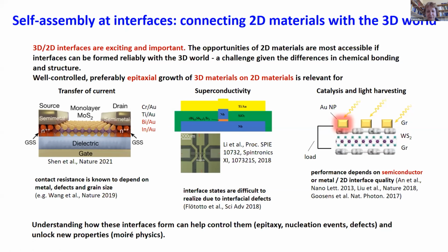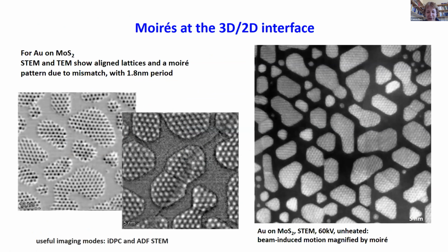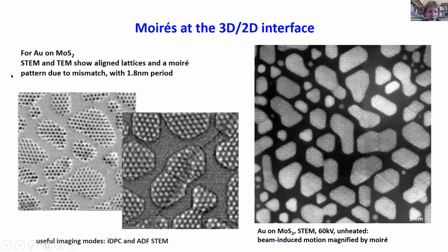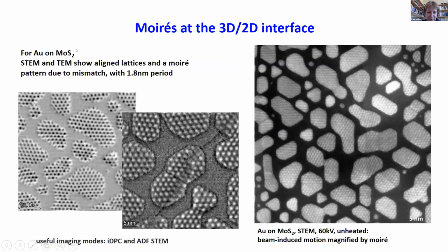And this is a great thing for the electron microscope, because we're trying to understand the relationship between crystals at the nanoscale, crystals that are very thin, and these make perfect TEM samples. Once you iron out some technical difficulties, you can see right through them, and you can get information on the growth of 3D materials on 2D materials. Right. So let's look at one of our favorite combinations: gold growing on molybdenum disulfide.